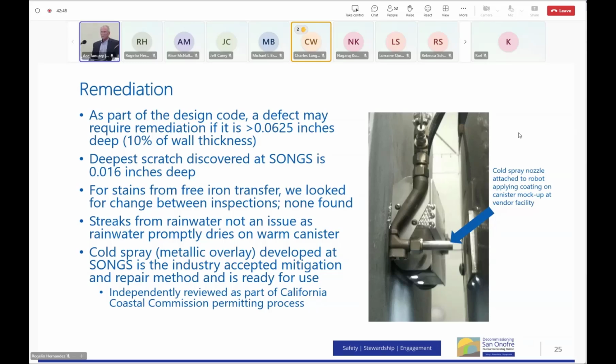We also had a test canister that we practiced with when we were getting ready to do the GTCC project at the TN system. And we put it, with the iron workers doing their thing, in and out like 50 times. And the scratches never did get more than about 15 thousandths deep. So that was really good to see that repeated insertions and removals doesn't cause the scratches to grow.